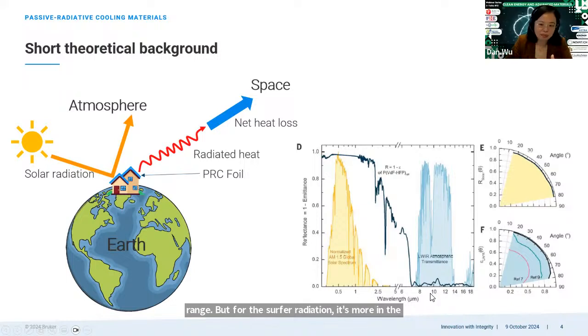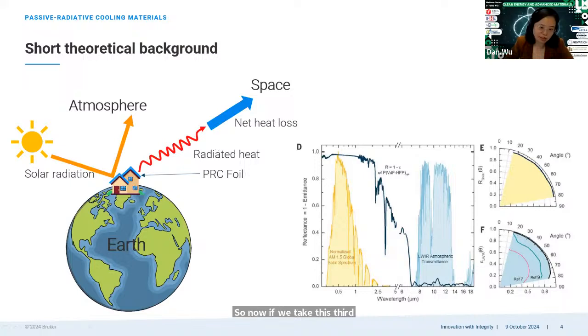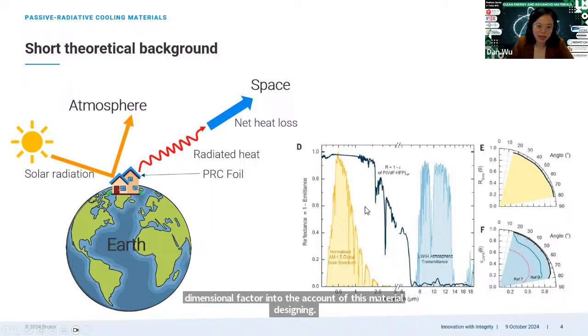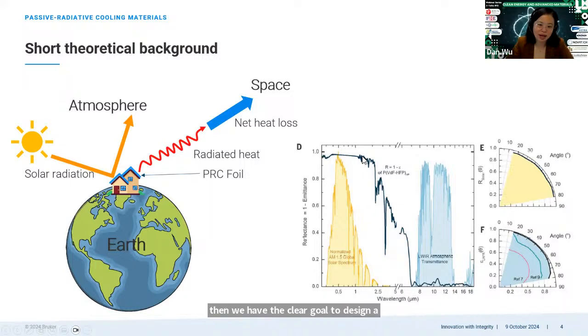If you calculate with Planck's theory, you will see that room temperature, like 30 or 40 degrees now, when calculated back to the wavelength range, is exactly located in the mid-infrared range. So if we take this third dimensional factor into account in material design, then we have the clear goal to design a material with high reflectance in the short wavelength range and high emission in the mid-infrared range.